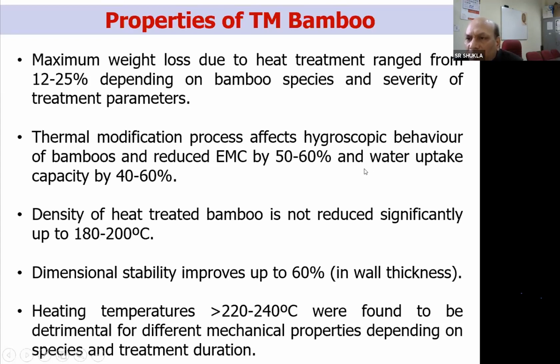That is, normally it is 10 to 12% or 15%, but after thermal modification, the equilibrium moisture content will be around 5 to 7% or 8%. And water uptake capacity will also go down by 40 to 60%. Density of the bamboo is not reduced significantly. There will be some reduction depending upon the treatment parameters, but drastic changes will not be there. However, dimensional stability improves by 60%. Like bamboo will become more dimensionally stable after the thermal modification. And much higher temperatures will start degrading the bamboo properties, particularly the mechanical properties of the bamboo will start going down.